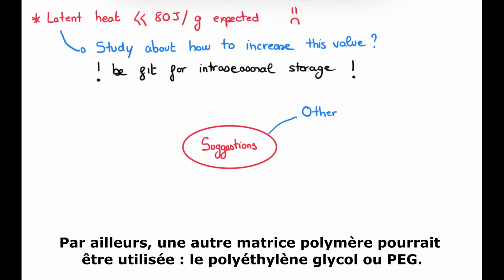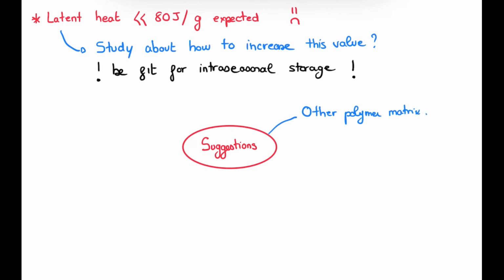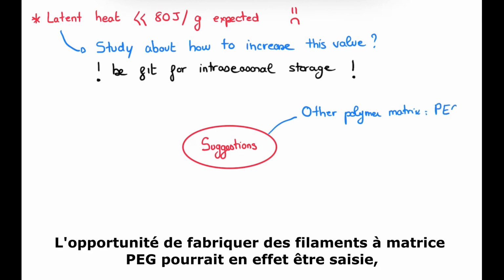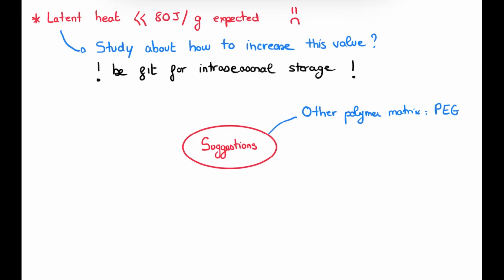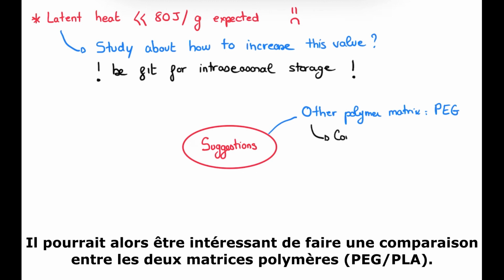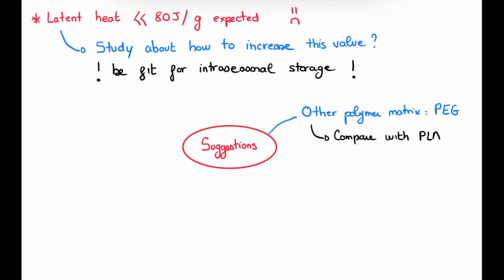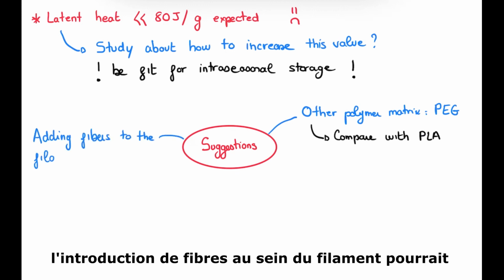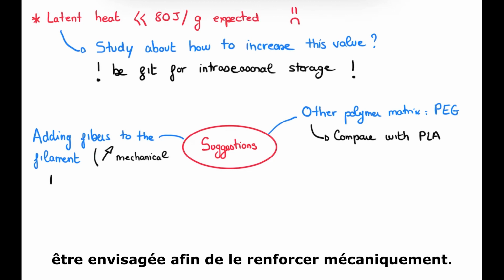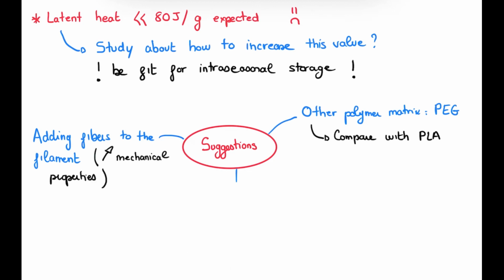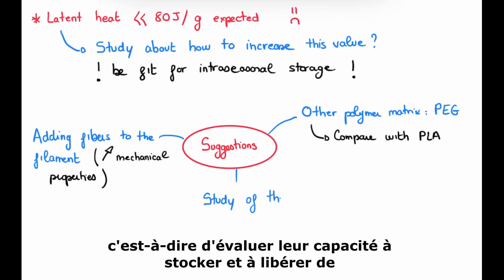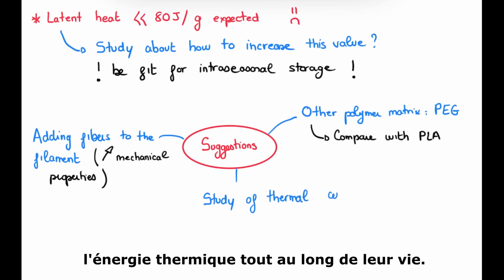Furthermore, another polymer matrix could be used, which is polyethylene glycol, or PEG. The opportunity to manufacture PEG matrix filaments could in fact be taken, as it meets the specifications. It could then be interesting to make a comparison between the two polymer matrices, PEG and PLA. Additionally, introducing fibers within the filament could be considered in order to reinforce it mechanically. Finally, it would be instructive to study the cyclical behavior of our filaments, that is to say, evaluate the capacity to store and release thermal energy throughout their lifetime.